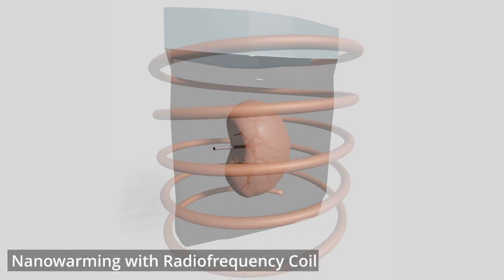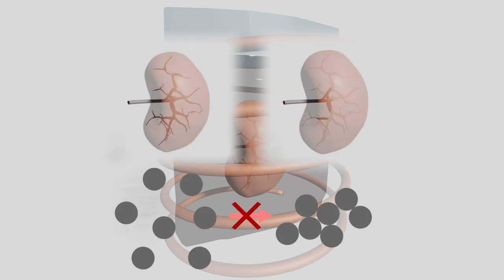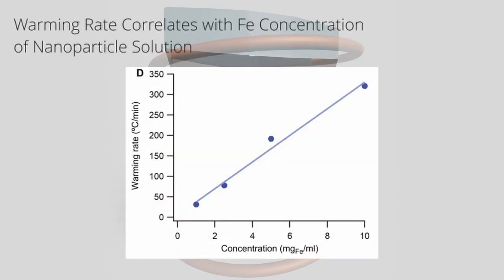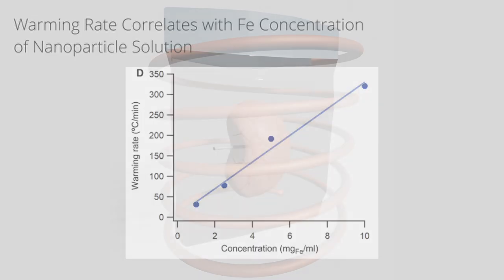To ensure even, fast heating, particles must be evenly distributed within an organ and well dispersed in solution, meaning not aggregated, to ensure heating rate isn't affected and blockages within vasculature do not occur during perfusion. Quantification of iron oxide nanoparticles and their distribution becomes important as concentration is directly proportional to the warming rate at a given frequency. This helps determine the ideal settings for rewarming to ensure cryopreserved organs are rewarmed quickly enough to prevent ice formation and organ cracking without damaging tissue.